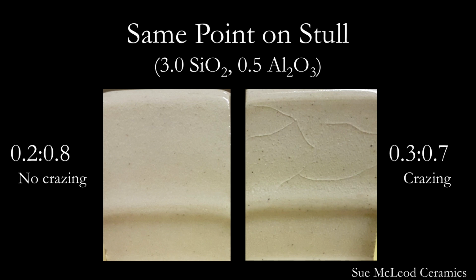These two tiles are from the exact same point on the Stull map. They have the same silica and alumina values, but different flux ratios. The sample from the 0.2 to 0.8 map has no crazing, where there is crazing on the 0.3 to 0.7 sample. This tells us that another way to get rid of crazing is to adjust the flux ratio, lowering the R2O flux while increasing the RO.